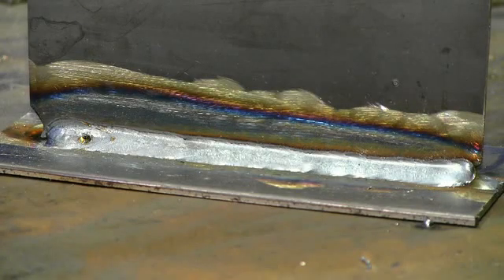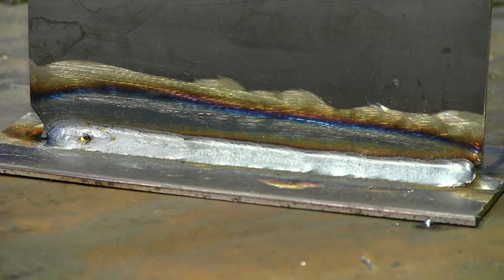Now during that weld, you could notice the very low spatter levels that were evident from good arc stability, and you didn't see the big BBs jumping out of the arc, for lack of a better term. And also you can look at the finished bead appearance, how it's very smooth, has a very flat face, and there's very little spatter on the adjoining plates. Now what little spatter does exist, it's easily brushed off with very little effort. So this is a very good spray transfer weld on 1/8 inch material.